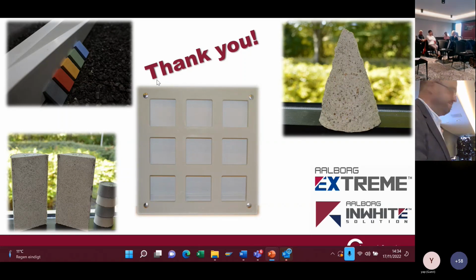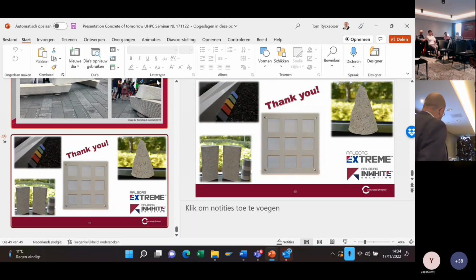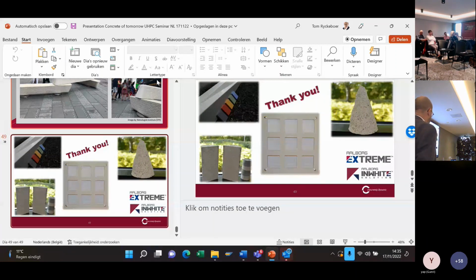Thank you, Tom. We have one question coming from the online audience. Could you please elaborate on the early age shrinkage of your material and from what time you consider that shrinkage is not solely plastic shrinkage anymore? Yes, there is a difference between plastic shrinkage and then the early age shrinkage until 28 days. We consider in this case, the figures we have are not the autogeneous shrinkage, and the plastic phase is not included in that.